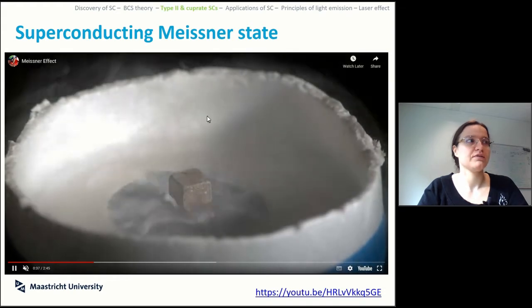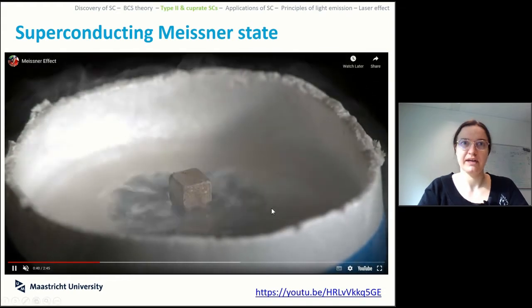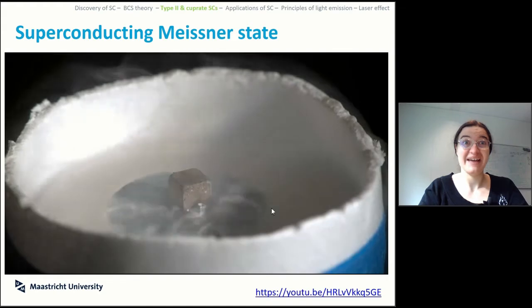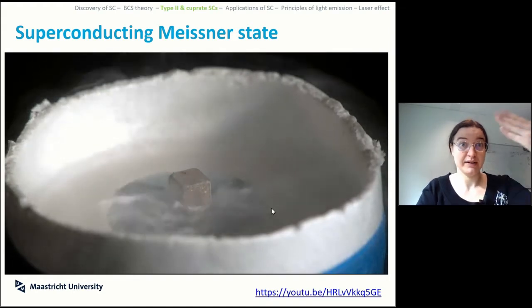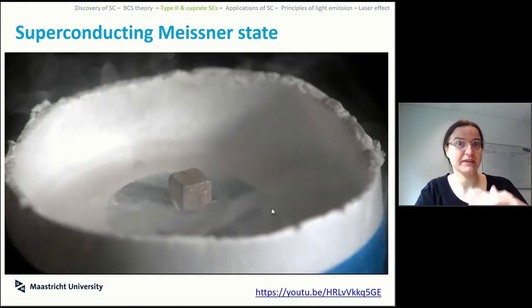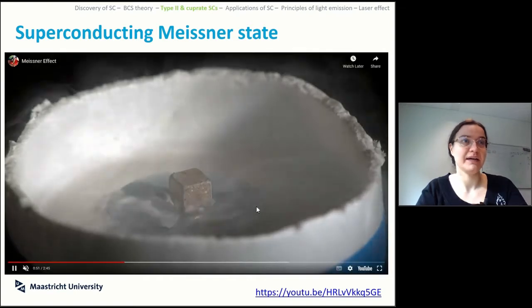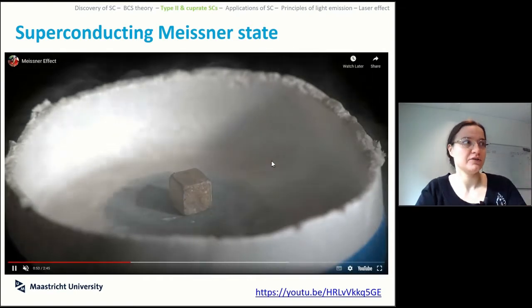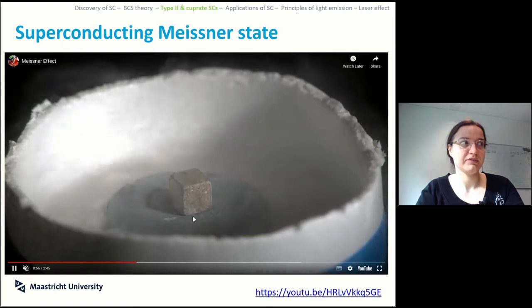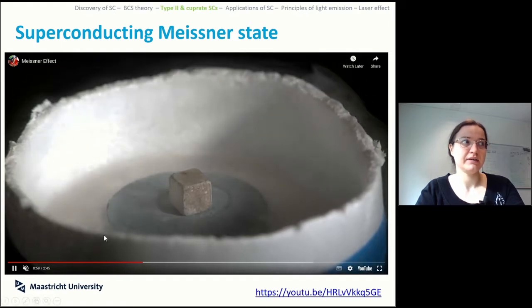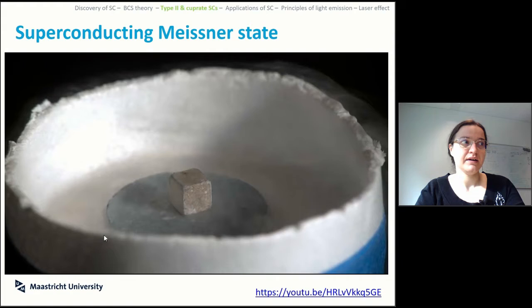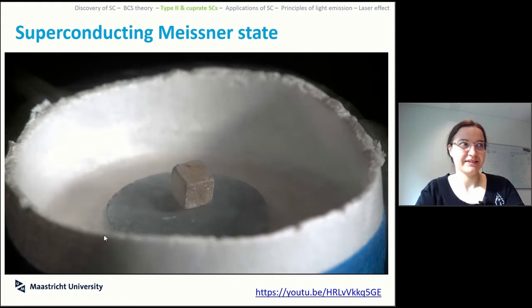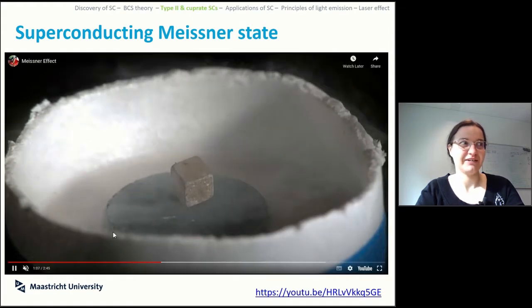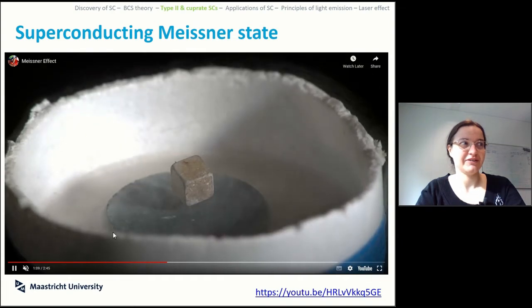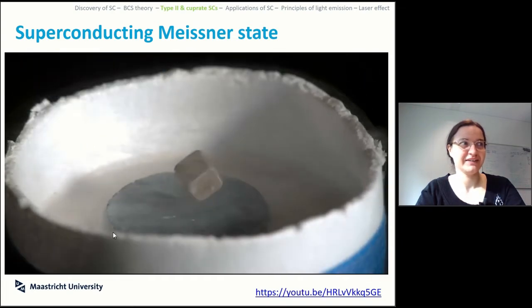Now you can see that the first part that you drop, it's a huge boiling point, because the liquid nitrogen needs to cool everything down. You want to bring all of your material to liquid nitrogen temperature. Everything that is keeping it hot is making it evaporate. But you can see that as it cools down the surroundings, the boiling of the liquid gradually decreases and the material slowly stabilizes. And now that it's actually at liquid nitrogen temperature, you can see that your magnet is suddenly floating on top of your superconductor.